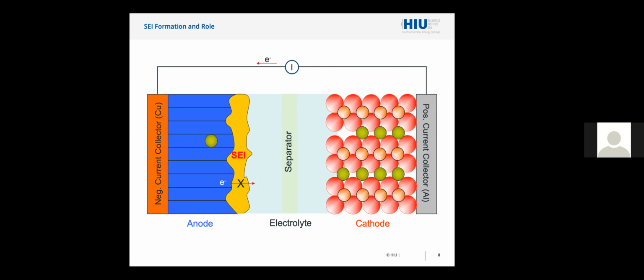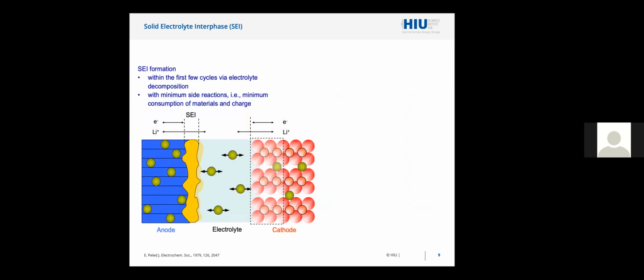Another great advantage, which I forgot to highlight, is that the presence of the SEI prevents solvent co-intercalation. So only lithium ions can go through the SEI and enter into the graphite structure, and this avoids the delamination of the graphite structure. So this solid electrolyte interphase is actually what makes lithium-ion batteries work. It's extremely important. It forms, hopefully, during only the first cycle, but anyway, just during the first few cycles, maybe 2, maximum 3.